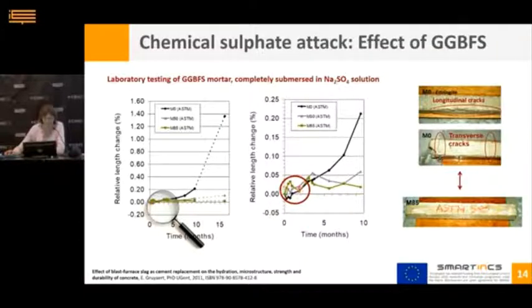It's a bit zoomed in on the right figure. We see not a steady increase, due to different reasons: the changes are within the accuracy of the measuring equipment, and we also did not coat the end faces, so we could have some crumbling that led to these fluctuations.